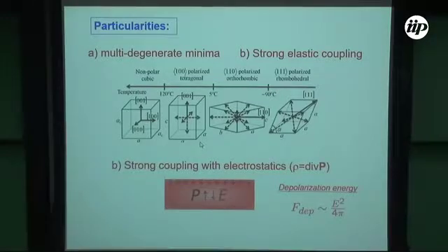So this somehow depends on the material, on the conditions, and even sometimes clamped and free material can give different displacement of the polarization vector. But what is important to us now is that the degeneracy is quite high, and there are even materials that can be somewhere in between, so we can make it more isotropic. And of course, it is very important and very interesting to have almost isotropic ferroelectrics, which are in a certain sense beyond some liquid crystal, because it can give very interesting things.